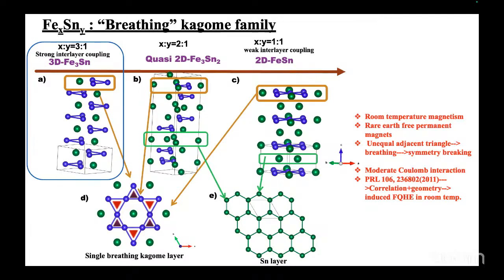But for the change in anomalous Hall conductivity, you need to see how the Berry curvature changes. The gap can change a lot, but the anomalous Hall can change only a little, depending on the curvature. We expect that by looking at the band features, which are different. The form of the band structure can change by a lot, but it doesn't mean that the Berry curvature changes a lot, because it depends on the total Berry curvature, not the local one. Yes, that is the future thing we look for, to find the Berry curvature.